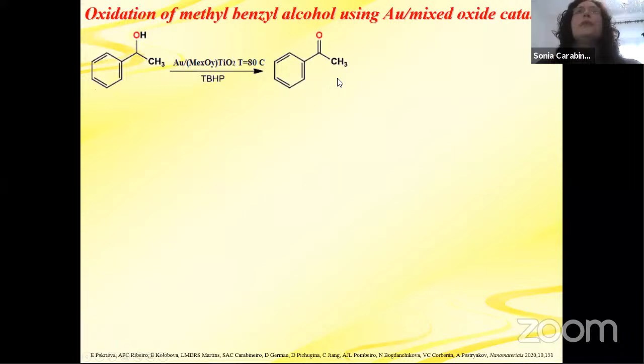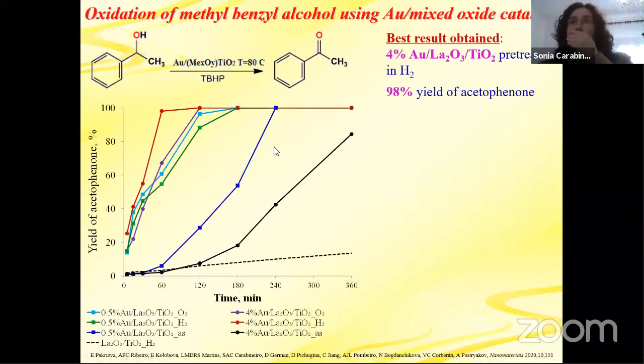So we have the oxidation of methyl benzyl alcohol using this gold on mixed oxide catalyst. So this is the reaction. It was performed at 80 degrees using an oxidant of tert-butyl hydroperoxide. So the best result obtained was with 4% gold on lanthanum titanium support pretreated in hydrogen, and we obtained a 98% yield of acetophenone. So here is the best catalyst.